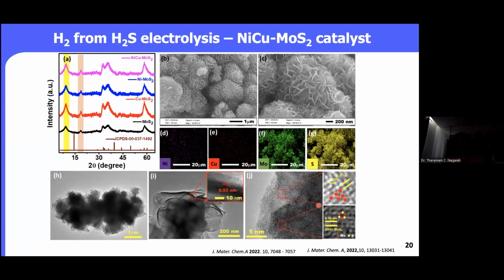To do this once, I'm just giving one example here, the nickel copper molybdenum sulfide catalyst, which has been synthesized by the hydrothermal treatment. As you can see by the XRD, the molybdenum sulfide shows mixed phases present. However, after the addition of either nickel or copper, we did not see any changes in the phases. This we confirm by the XPS also, due to the addition of the electronic properties changes after the addition of nickel copper.